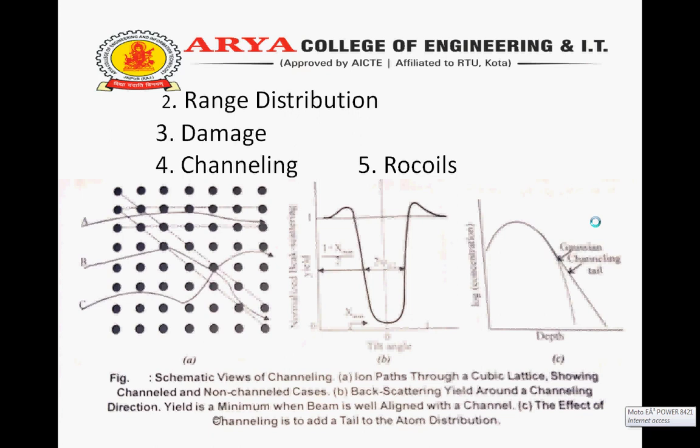The binding energy of a lattice site is only 10 to 20 electron volts, so it is easy to transfer enough energy to free an atom from its position. Now both the ion and the displaced target atom travel and cause further displacement. So the energy is spread over many moving particles. Eventually, the energy per particle becomes too small and the cascade stops.